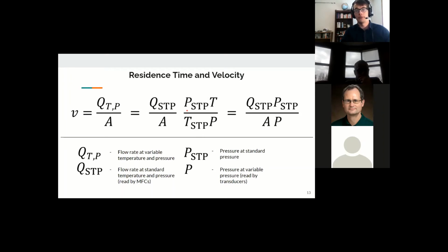P_STP is equivalent to about 760 torr, because that's just the pressure at standard pressure. And P is the pressure measured by the pressure transducers in our system. A is the cross-sectional area of the reactor. And the final part of this equation implies that this is a non-thermal plasma, or that the temperature that we're operating at is equal to standard temperature, which is room temperature. So using the velocity found in this equation, the Reynolds number can be computed. And for the 0.69 inch inner diameter tube, the flow ends up being transitional between laminar and turbulent flow in the reactor.